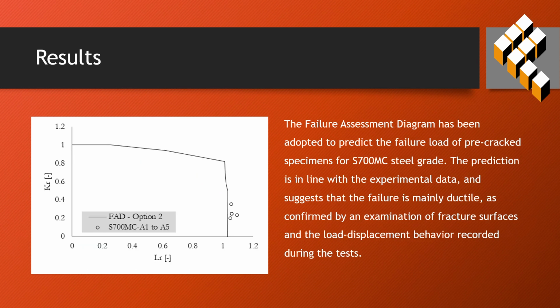The failure assessment diagram has been used to predict the failure load of pre-cracked specimens. The prediction is in line with the experimental data and suggests that the failure is mainly ductile, as confirmed by an examination of the fracture surface and the load displacement behavior recorded during the tests.